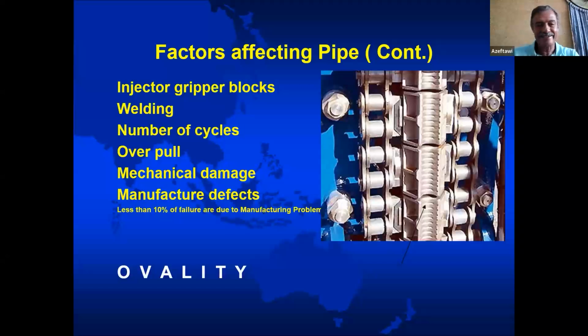Why? What am I saying? The technical data sheet you received from the manufacturer is based on the fact that the pipe you received is a round pipe. It has one diameter. So if you measure any place, if this is 1.5 inch, if you measure it anywhere, it is 1.5 inch. But after you make the first run, the pipe is not round. The pipe is oval. You won't see this by naked eye. There is a device that can measure that. But after the first run, the pipe has two diameters. It has D maximum and D minimum.